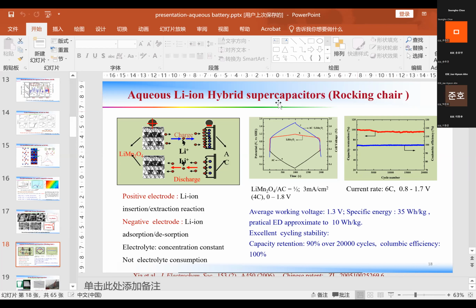For the conventional supercapacitors, normally the electrolyte will be consumed in the charge process. But for this hybrid lithium-ion supercapacitor, in the whole charge process there is lithium insertion and extraction reaction in the cathode material, and in the anode, the activated carbon, there is ion adsorption or desorption. So the electrolyte concentration is constant, no electrolyte is consumed. This mechanism is quite different from the conventional EDLC, electric double layer capacitance.